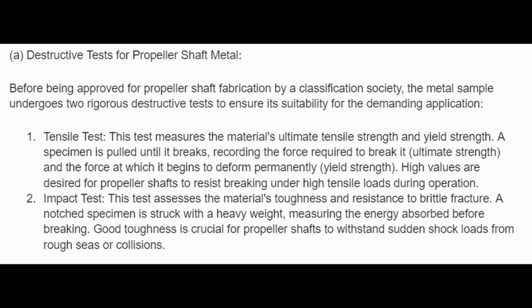Before being approved for propeller shaft fabrication by a classification society, the metal sample undergoes 2 rigorous destructive tests to ensure its suitability for the demanding application. 1. Tensile test. This test measures the material's ultimate tensile strength and yield strength. A specimen is pulled apart until it breaks, recording the force required to break it, the ultimate strength, and the force at which it begins to deform permanently, yield strength. High values are desired for propeller shafts to resist breaking under high tensile loads during operation.